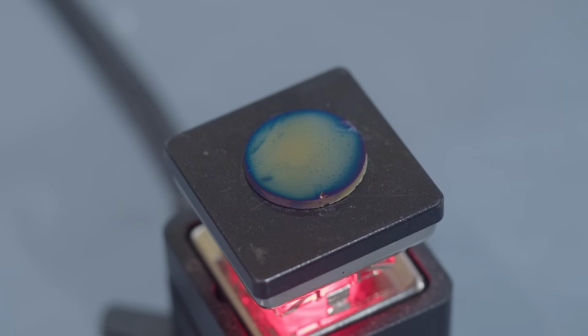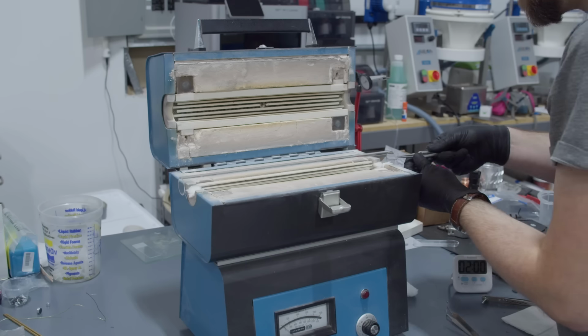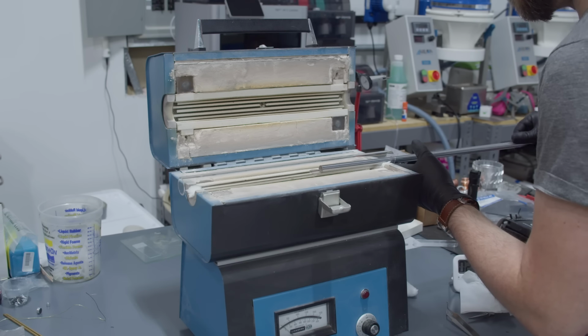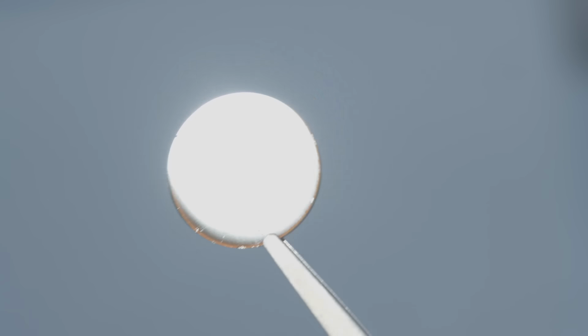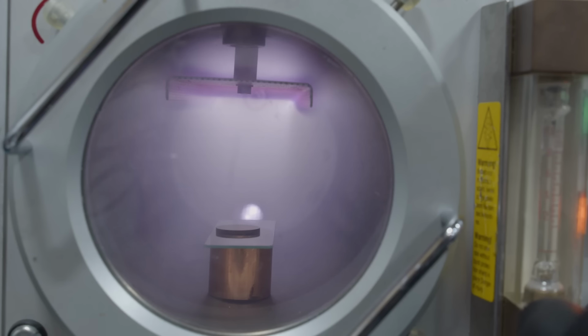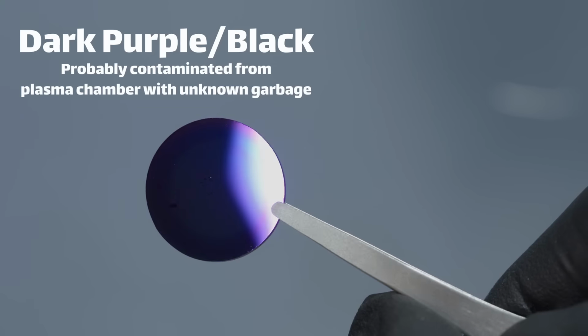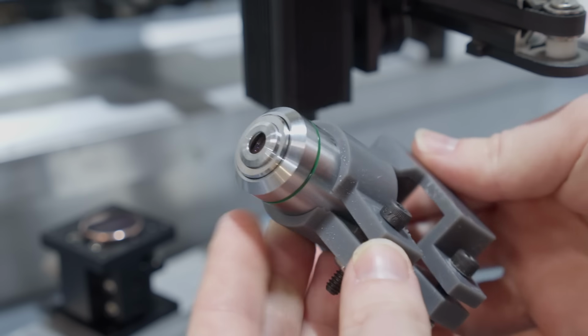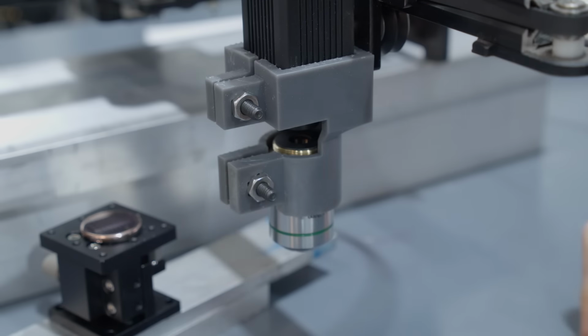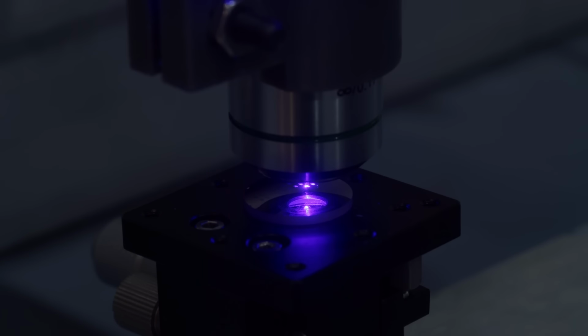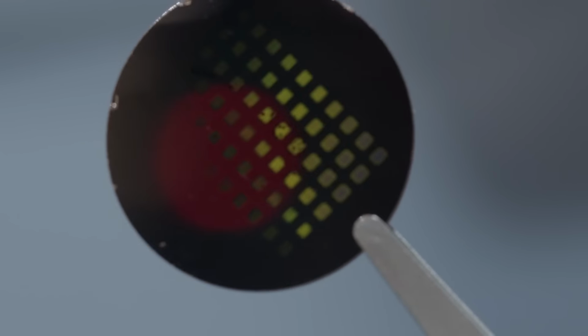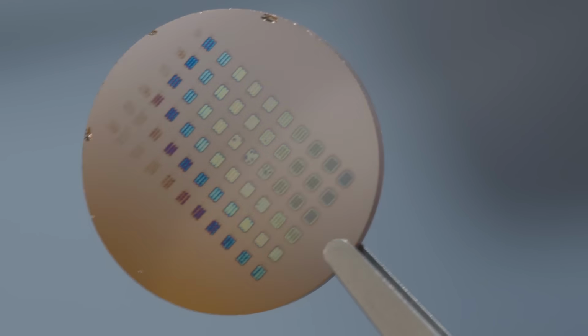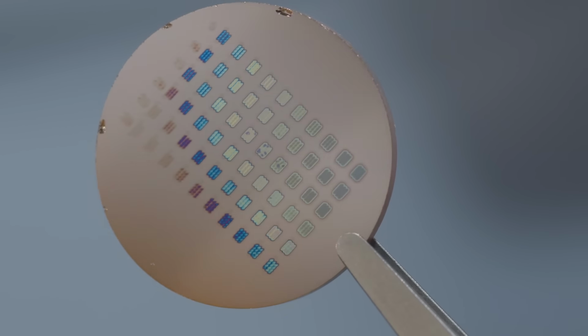One sample was oxidized at 200 degrees on a hot plate and should in theory be mostly copper 1 oxide. Another sample was oxidized at 600 degrees in the furnace and should be mostly copper 2 oxide. These samples were the main goal, but I also included a sample that was oxidized in oxygen plasma and another that was thermally oxidized using a laser. Laser processing could be really interesting for future experiments. The furnace oxidation technique is really effective and simple, but it's slow and difficult to integrate with other steps just due to the temperatures involved. In contrast, locally oxidizing with a laser is super fast and can be targeted to specific areas.